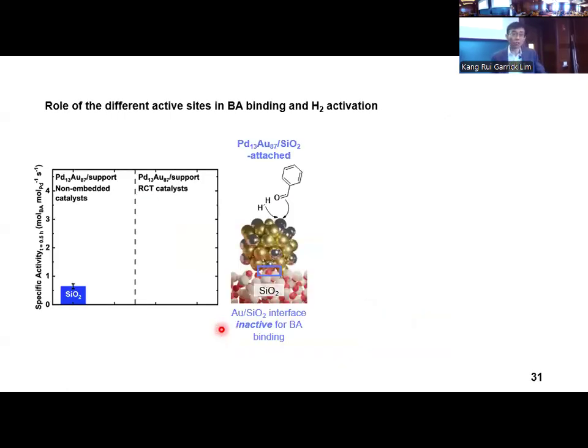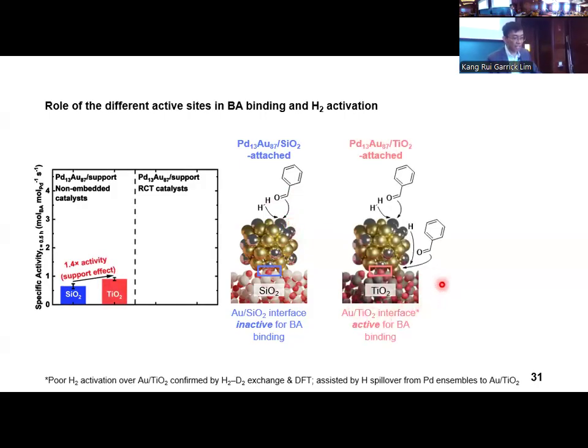We can now summarize the roles of the different active sites for benzaldehyde binding and hydrogen activation, the two key elementary steps in catalytic benzaldehyde hydrogenation. In the non-embedded silica catalyst, its modest activity was derived from palladium ensembles on the nanoparticle surface that activated hydrogen and bind to benzaldehyde. When the support was changed to titania, the activity was enhanced slightly due to additional benzaldehyde binding at the gold-titanium interface on top of benzaldehyde already bound to the surface palladium ensembles on the nanoparticles.